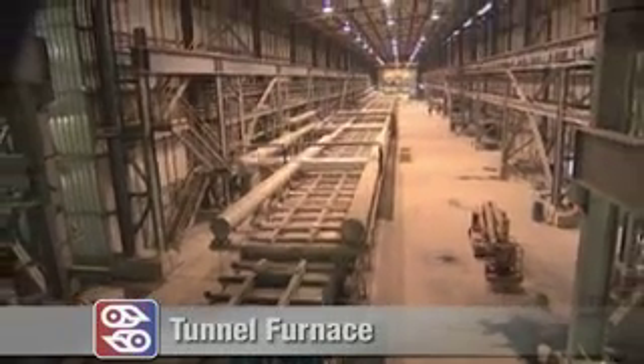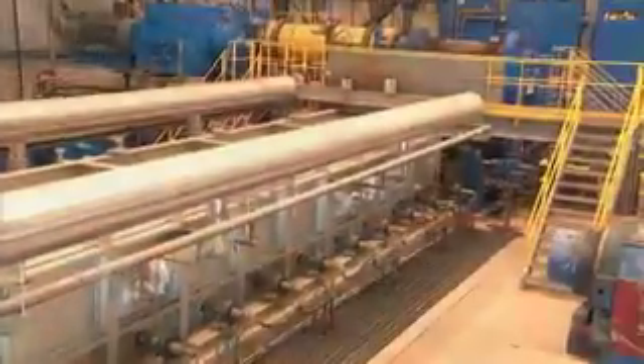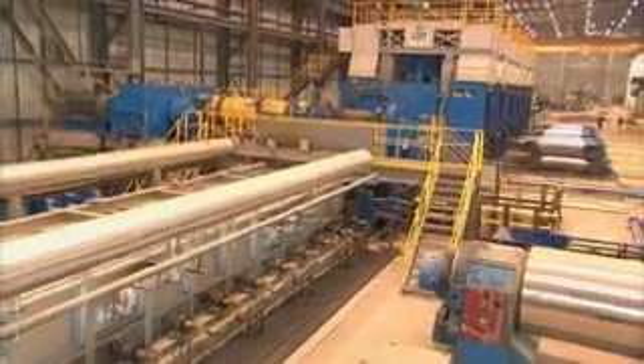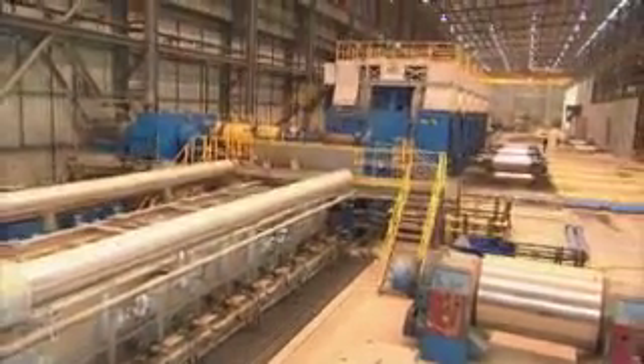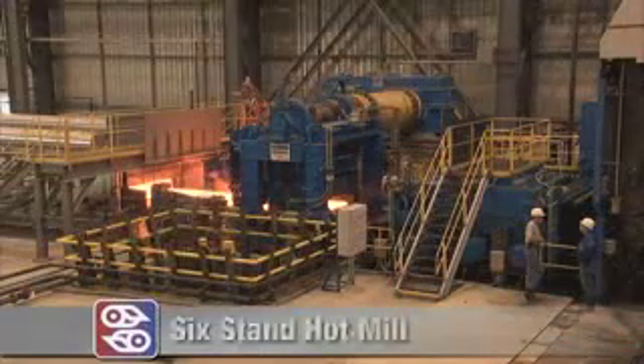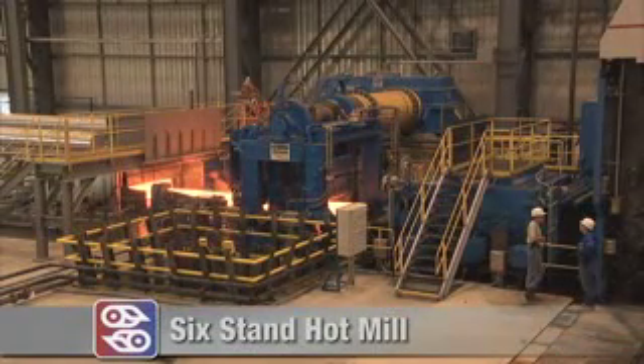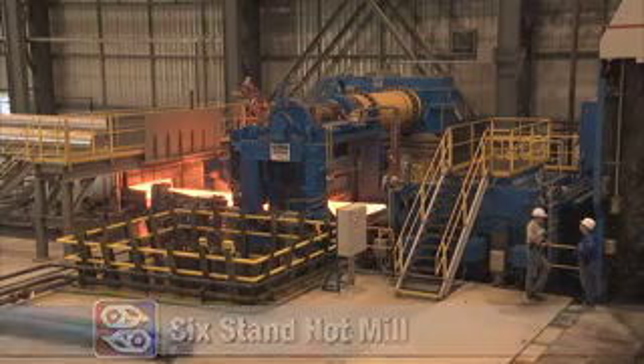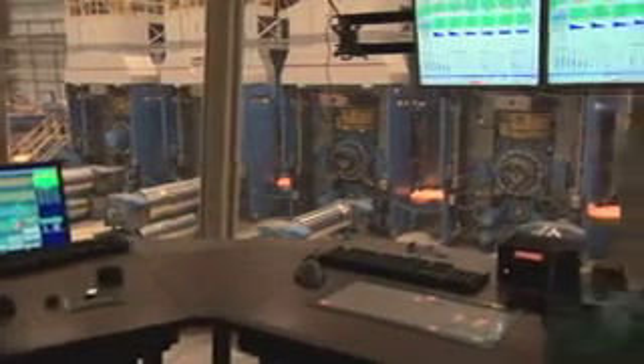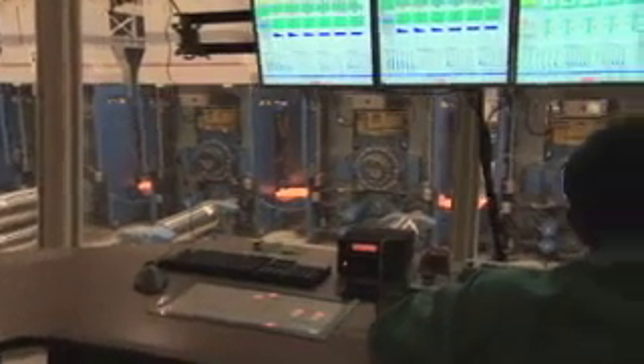Nearly the length of 3 football fields, the furnace heats the slab to a consistent hot rolling temperature of around 1,900 degrees Fahrenheit during its 15-minute journey to the hot mill. Leaving the furnace, the slab enters the 6-stand hot mill, where the 2.5-inch slab is reduced as specified by order to thicknesses from 1/2 inch to as light as an 0.054-inch gauge, or about the thickness of a US dime coin.